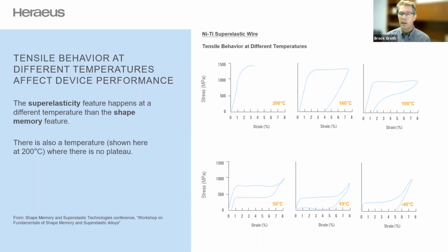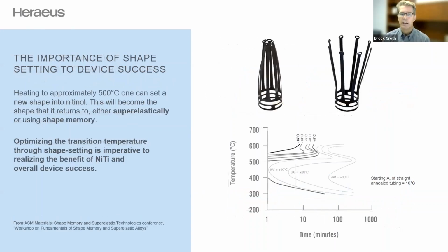And what's happening here is that at this temperature, the force needed to stress-induce martensite, which is how you get superelasticity, is so high, it's above the force needed to create classical slip dislocation deformation. And so you don't get superelasticity or shape memory, you just get kind of a conventional behaving material at higher temperatures. Again, there's nothing magical about these temperatures, it's just for example's sake. Different materials will behave on this spectrum, but the curves will be slightly different. Move on to the next slide.